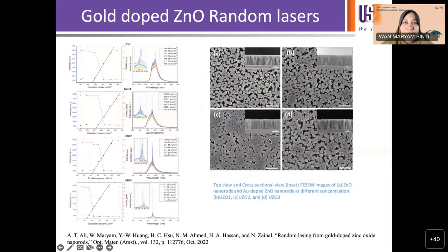So these are the things that we have done. Most recently, we've just received the email of this publication on Sunday. So this is the most recent work that we did together, and it's by looking at gold doped random lasers, which shows quite good lasing characteristics as well, again with the highest doping of gold that is possible in the chemical bath deposition method.